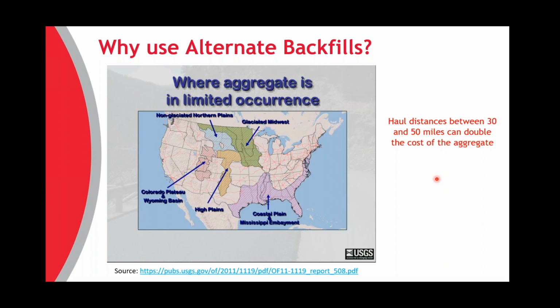And I can attest to this because where I live right here in southern Alabama on the coast, our stone price is about $40 a ton delivered. And that's mainly because we don't have locally available stone in this area. We have to either barge it in or truck it in from a long way away. If you go to the central part of the state, just outside of this zone that they've indicated here, stone is much more plentiful, and it's about $15 a ton. So it's a huge difference just due to transportation costs.